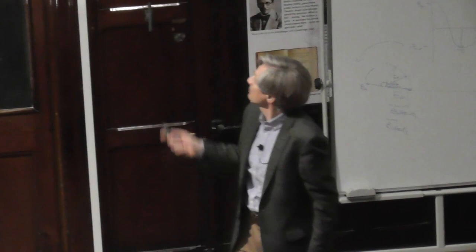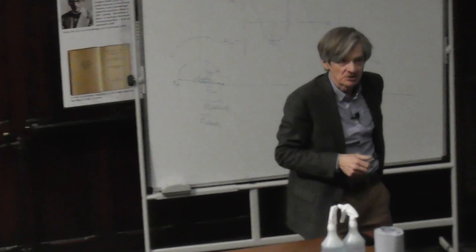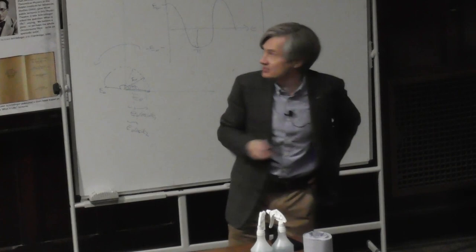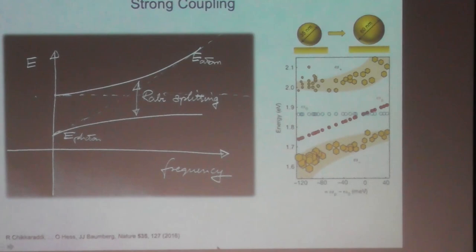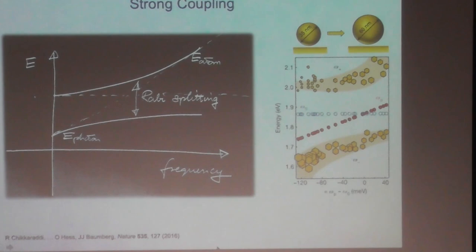We don't have our quantum processors yet, but we are on the way, because what we have in this tiny gap, which means nanotechnology and photonics, can open up quantum processes on scales that otherwise would only be exhibited in cryogenic temperature domains. So that's literally what this cavity is. It's open, but it contains that molecule. This is now an experimental plot, and we designed that a couple of years ago. It was, for us, a revolutionary step forward to demonstrate that this strong coupling event, where light and matter work together, was possible at room temperature rather than at cryogenic temperatures.